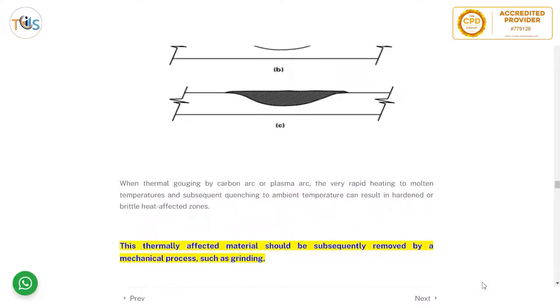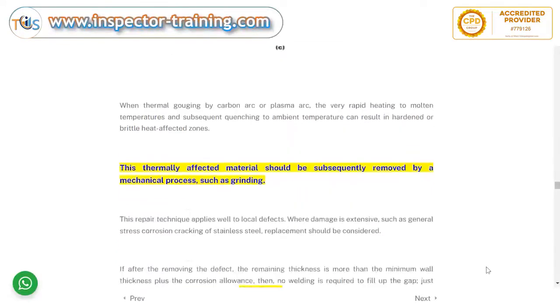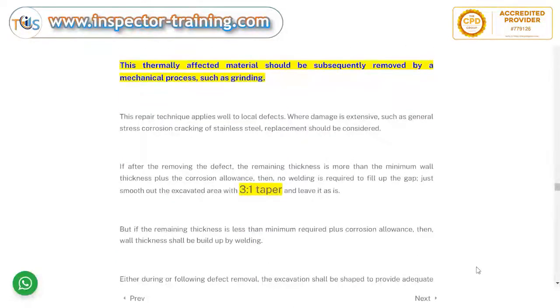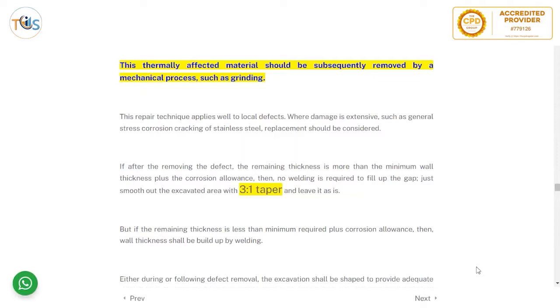When thermal gouging by arc, carbon arc, or plasma arc is used, because of very rapid heating to a molten temperature and subsequent quenching to ambient temperature, the heat affected zone can become hardened or brittle, and this thermally affected material should subsequently be removed by a mechanical process such as grinding. This repair technique applies well to local defects. Where damage is extensive, such as general stress corrosion cracking of stainless steel, replacement should be considered.